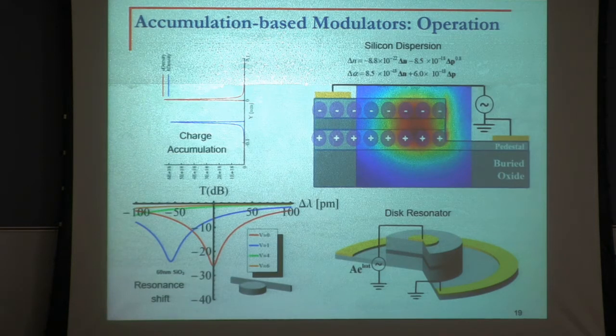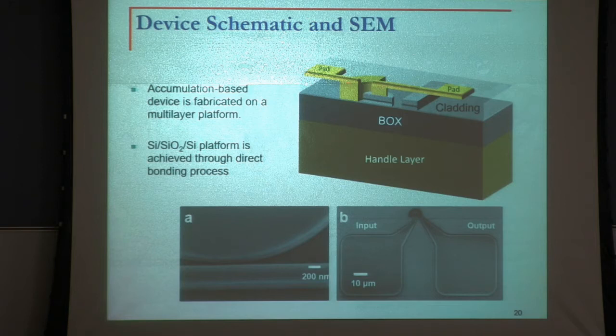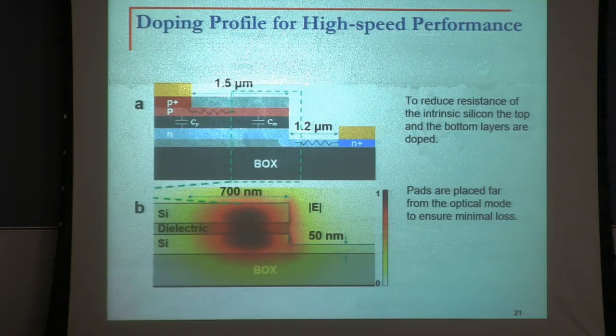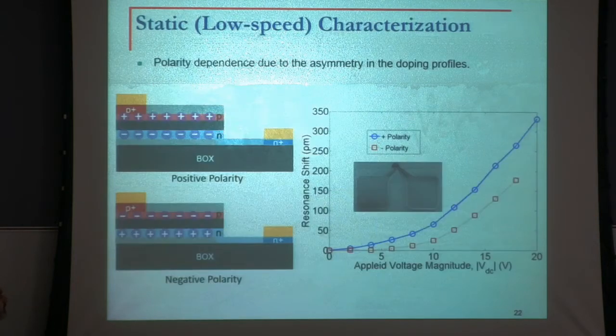And most importantly, if there is any problem in the size of the resonator and its resonance wavelengths, all I need to do is to apply a DC voltage, to put some DC carriers in, and then fix that problem without keeping a current in all the time or keeping heat in all the time. So that allows me to reduce the power consumption of the device. This is the design structure as shown over here. Adding the contacts is always a challenge because you have to add them in a place where the electromagnetic field is minimum. And then this is the RC structure that you can see. There are some resistances in the structure. And depending on the resistances and the capacitances that are involved, you will get an RC time constant which defines your speed of operation.